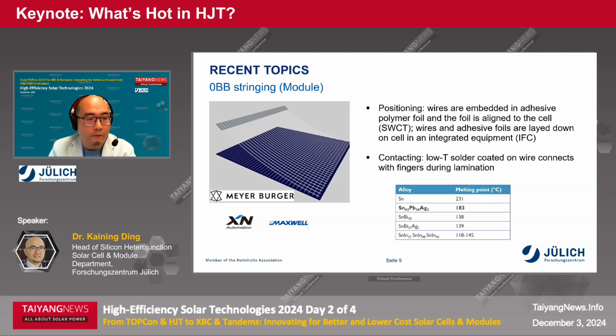And in the case of XN Automation and Maxwell, they are doing it slightly differently. The wire positioning and adhesive foils are not prepared beforehand, but they are adjusted and laid down on the cell in the integrated equipment. So the wire and adhesives are laid down on the cell in the same equipment. They call it the IFC approach. But the contacting is the same idea. The contacting happens during the lamination, where the surface alloy coating is melted and that makes a connection between finger and the wires.